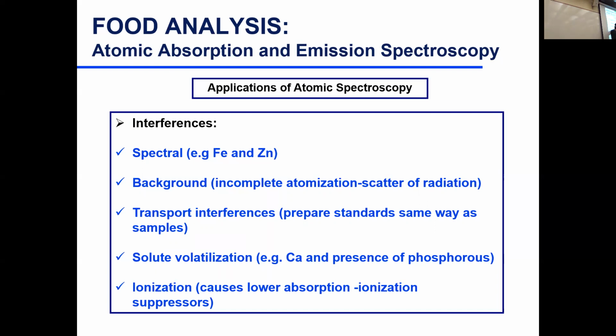Background, this is a cause for overestimation. So you have a question in your lab report, what can cause overestimation? Overestimation can be caused by incomplete atomization. So if the flame is not hot enough to break the bonds, if the acetylene to air ratio is not the right ratio, acetylene is the fuel, air is the source of oxygen to ignite to produce the flame. If you don't have the right temperature, your molecule might not break. So the molecule is going to scatter light.